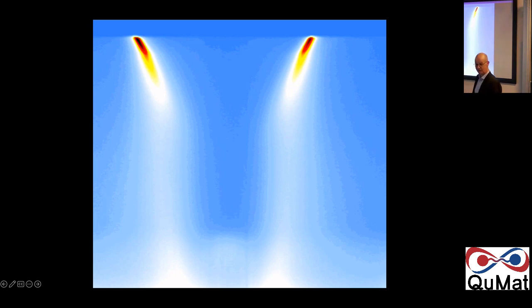So this is an example of a data set. It's one of the best ones we ever measured. So this is about 3 hours of just really willing yourself not to press OK on the computer and stop it, because you don't notice as this is scanning after the first 15 minutes, you don't see it getting better anymore. So you have to keep downloading the data, zooming in and looking at these little contours in the background, which are really, really perfect. This experiment has been done on this material since 2000. We were doing it in 2020, so you better do it better than anyone else has done it. And otherwise, what's the point?